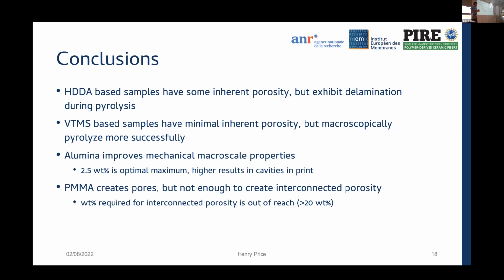Finally, PMMA does create pores, but at the weight percentages that were successful in printing, this is not high enough to create interconnected porosity. Further, this is in agreement with some literature as well. And in just looking at it, you need higher amounts of additive to get that interconnected porosity. However, from a macro scale, there was success in improving the mechanical properties over the summer, improving the lack of cracking.